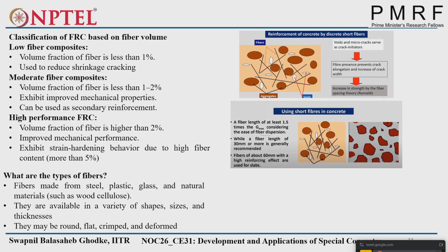But what happens if you have these voids and only here you have the fiber, and this side there is no fiber? If it is widening, do you think it will be resisted by the fiber? Will it be resisted by the fiber content or fiber matrix? No, because there is no fiber available from the other side. So widening will be possible from the other side. So that's why